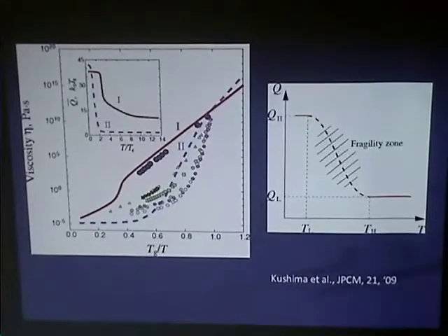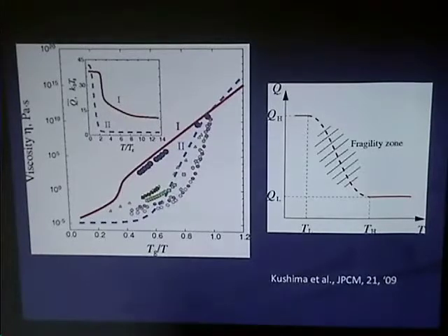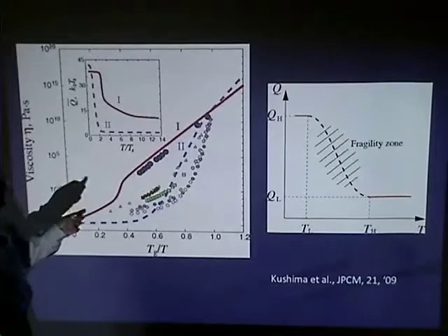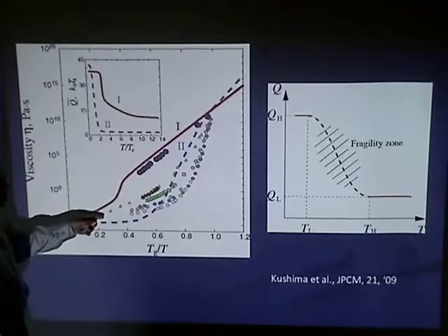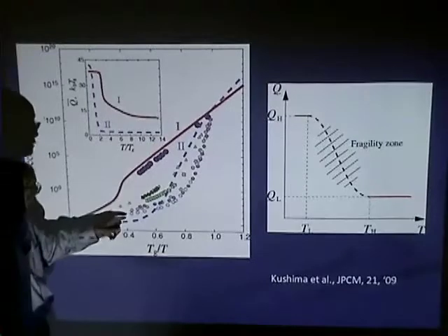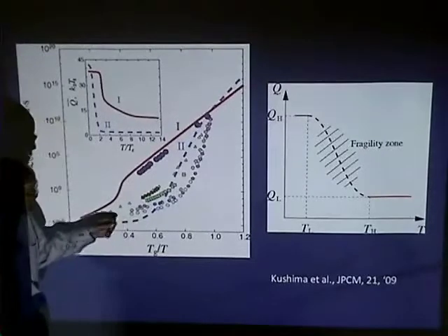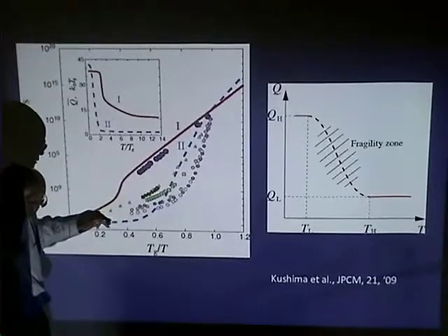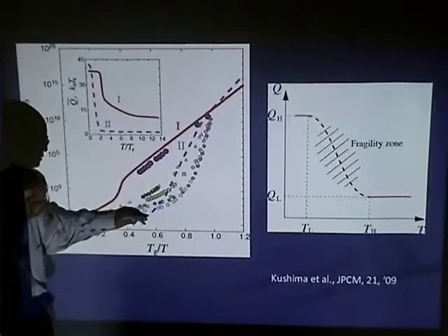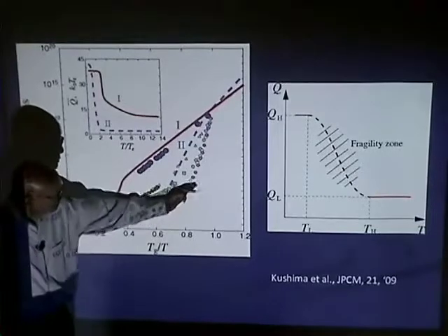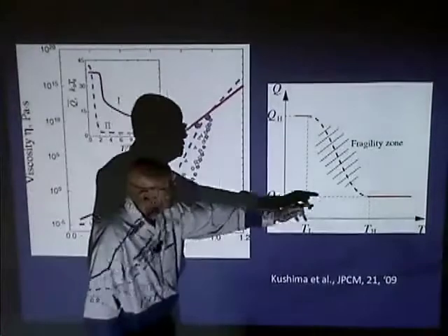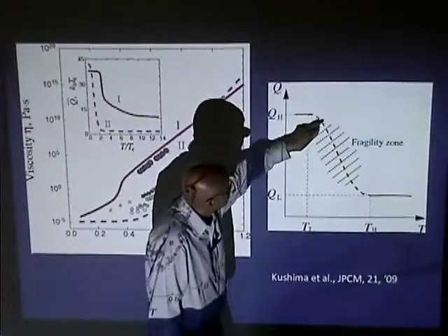Okay, but I'm still not quite clear why your curves have to have this S shape rather than just having a low slope on the left and a high slope on the right. I don't quite see it. I guess we have to talk a little more, but offhand, there's plenty of data from experiments which tell us that at high temperature you start out with fairly Arrhenius behavior, and then you go into this bending up, which is this one here. So there's plenty of data for that. There's some data now that's starting to suggest this happens.